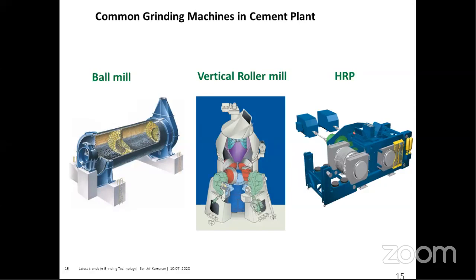If, for example, I already have a ball mill in my system and I would like to upgrade it, then without demolishing the complete ball mill setup, people would normally prefer to install the hydraulic roller press system. Thereby it increases the production, lowers the power consumption, and improves the performance of the system. If it is a standalone system, then people prefer vertical roller mills as well. Based on location, if I want to put up a plant in Gulf countries where there is more water scarcity, I may not be able to operate the vertical roller mill efficiently. So in those areas, people prefer hydraulic roller presses.